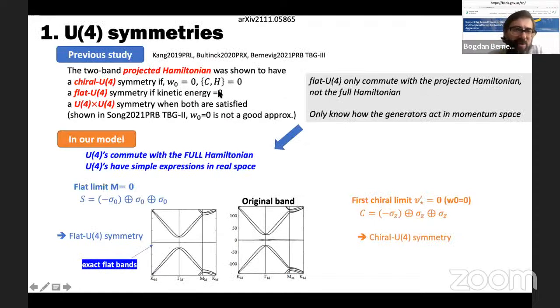The first thing that I wanted to show you is that there's a large symmetry in this model, and the large symmetry in this model is actually reminiscent of some large symmetries that other people like Kang and Vafek showed in the projected models, which are strong coupling models which only project into the flat bands. The advantage of this is that these symmetries now actually commute with the full Hamiltonian, with the kinetic part also. So for example, if I take what we call the flat limit, so this mass term, which was the bandwidth of the Bistritzer-MacDonald model, which is 3.7 milli-electron volt, something like this, times 2, if I take this to be 0, then you'll get a U4 symmetry in this model.